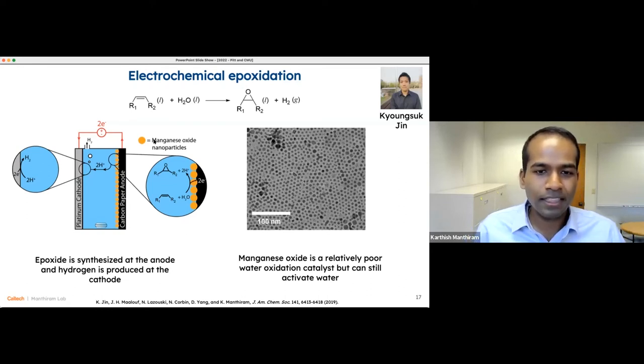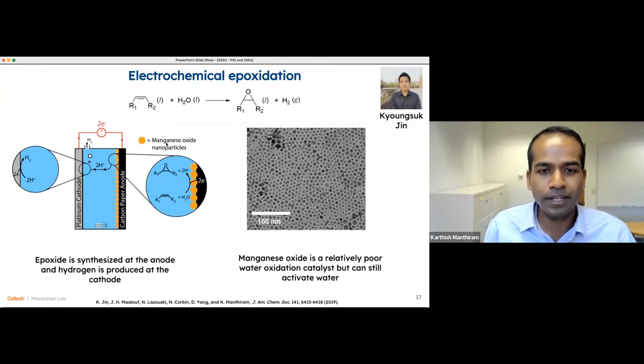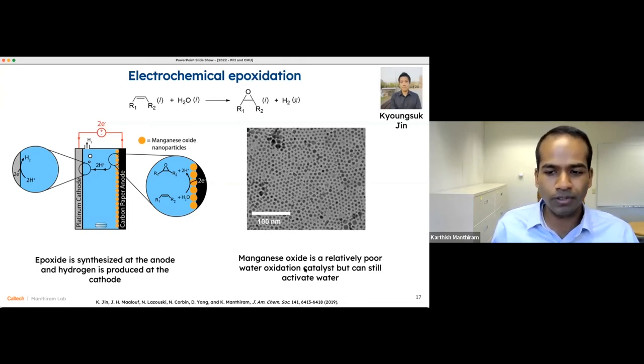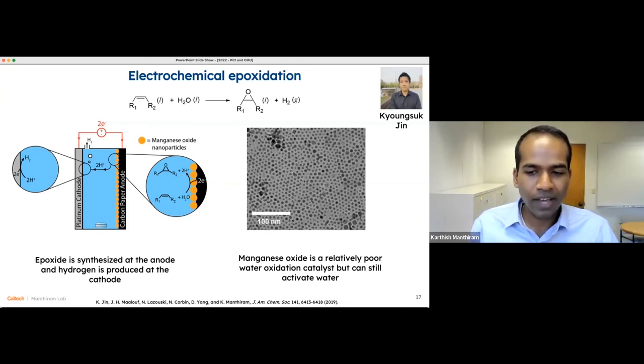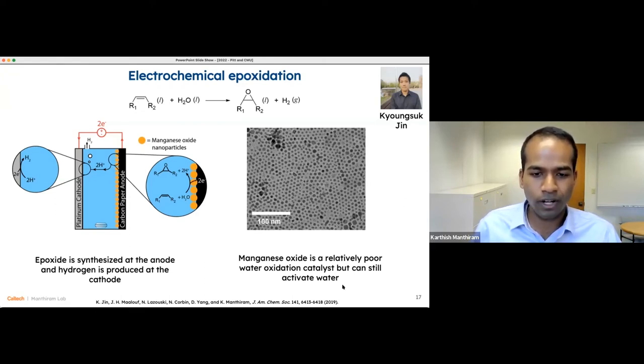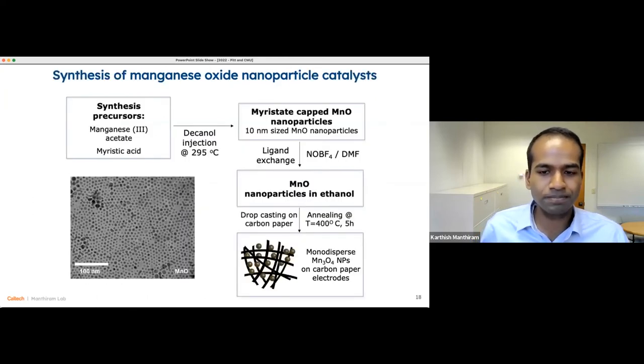So we reasoned that manganese oxide could perhaps be an attractive catalyst for this reaction. It is relatively poor at water oxidation, but we liked that because that would help to suppress O-atom-O-atom recombination, so we could suppress O2 evolution, but it can still activate water, and that's something that's been shown in a series of prior studies in the literature, that it can in fact activate water. So we thought that manganese oxide could be a good catalyst for this reaction.